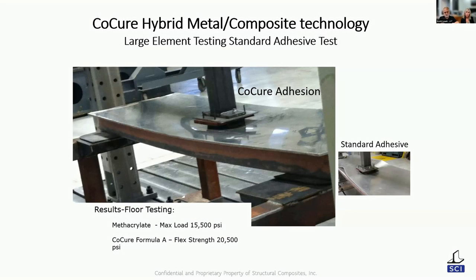And carbon will do it, but glass is $1.50 a pound. Carbon's 20, 25, $30 a pound. It just knocks our budget out. So the discovery we made with Wabash on metal co-cure hybrids really was a home run. So now what we're doing is we're marrying the composite to the metal. We're stealing properties like modulus out of that and really coming up with a way to get traditional materials displaced, ironically, by using a bit of traditional material.